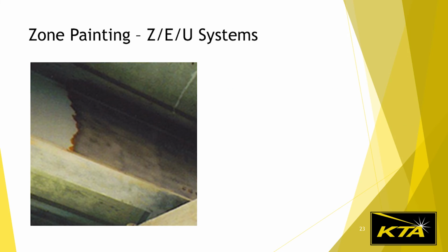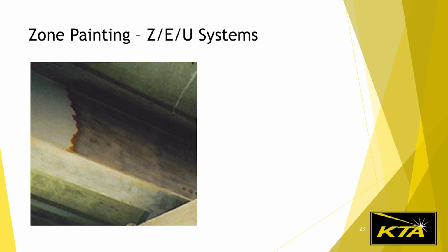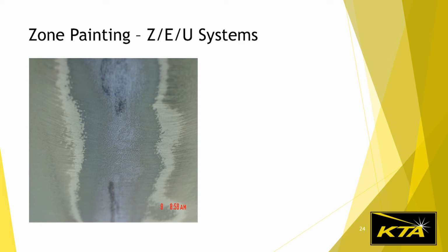I'll show you a repair area in a couple of slides that shows what the feathering should look like. To get a nice clean line, the contractor should be using a rubber mat or some kind of barrier at those areas. But I've also seen them use a blast nozzle and just blast them back towards the abutment or pier, whatever they're blasting towards. Here's a photo of what I just talked about. They didn't use a barrier there. And although this isn't a zone transition, it's a repair area. You can see the bare steel, and then you can see the zinc primer, the intermediate. So that's what the feathering should look like to tie back in.